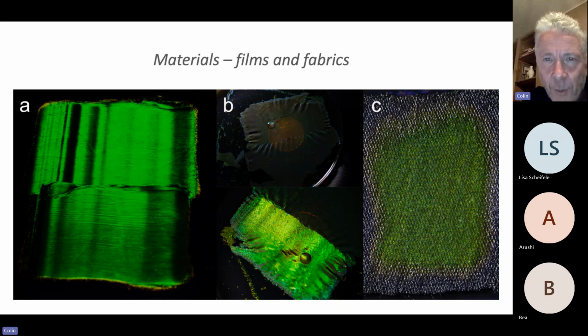B, the top and the lower part, is really fun. This is what happens if you float the film that you see in A off the plate, and it's not easy to do. What you're seeing in B is the film floating on water. Underneath the film is, I can't remember, a 25 euro cent EU coin. And you can see that it's transparent. If you look at it from a different angle, the bottom panel in B, it's reflective. So you've actually created a material which, by how you've orientated the organism, reflects light in a very specific, very selective way. So it's quite a sophisticated thing.